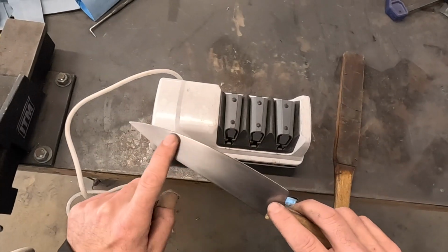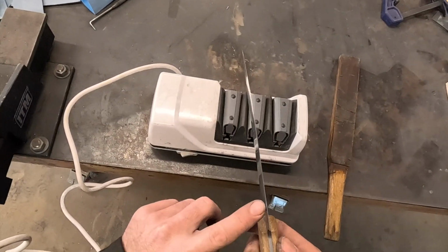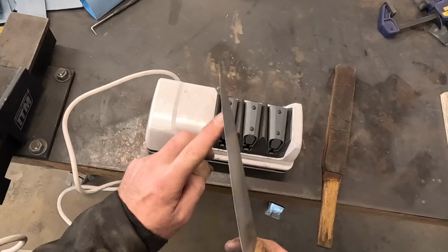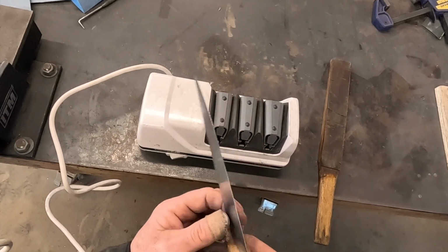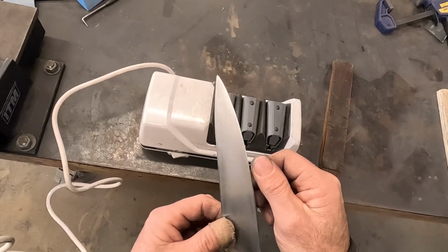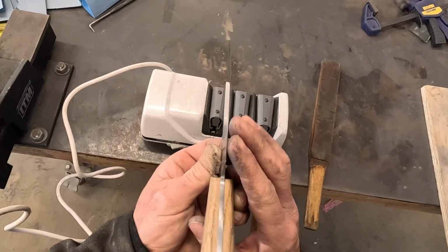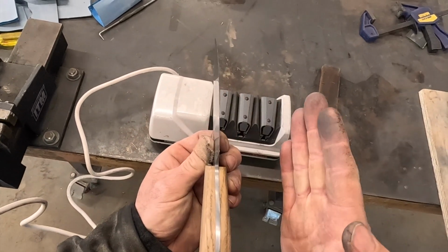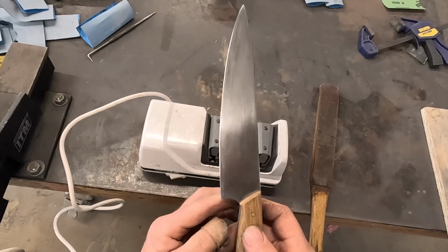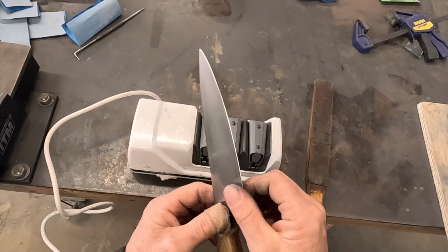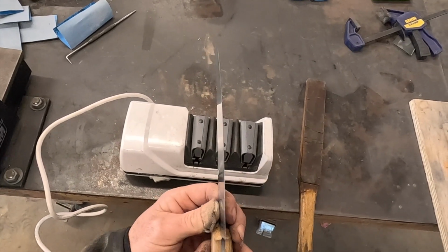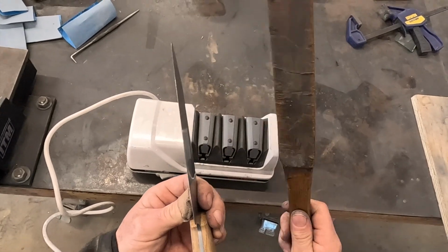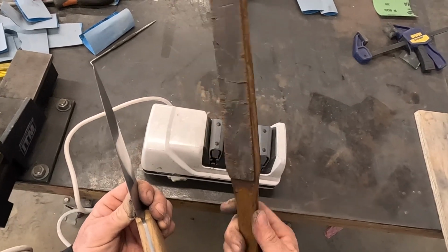We're looking for a nice even bevel forming on each side and consistency in thickness of the blade edge. Over time, what's called a wire will develop along this front edge, and it's where the metal comes up into a point and starts to almost break off. We work along these stones until that wire is almost gone, and then we knock the last bit off with a strop. Our strop is just a piece of old leather glued onto a stick.